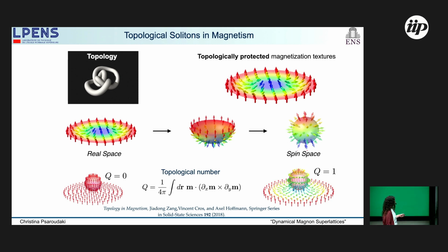If we do the same for the ferromagnetic state where all the spins point up, of course here we just have a charge that is 0, and this state is separated from the skyrmionic state by an infinite barrier in the ideal case. So that's the concept of topological protection. Once we realize a magnetic skyrmion, it's very hard to destroy it. Of course, that's a concept that exists only in theory. In a real material, we have defects and other deformations that lower this energy barrier, but still skyrmions are quasi-particles that have relatively long lifetimes.